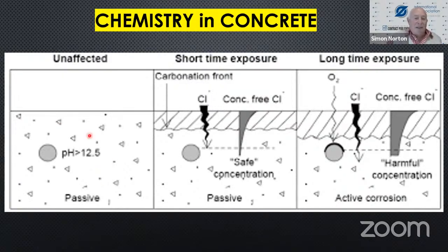Now, if you're sitting at Cape Town or Durban, Port Elizabeth, or on the coast, or you're in an area where there's substantial wind or effect of the atmosphere in movement, and it's not a still environment, and it's an open atmospheric environment, gradually you will get a change that occurs in the concrete. And what happens is the carbon dioxide in the atmosphere starts to penetrate the porosity of the concrete to form a carbonation front, which you see here.